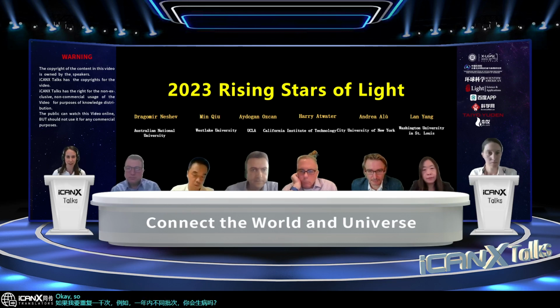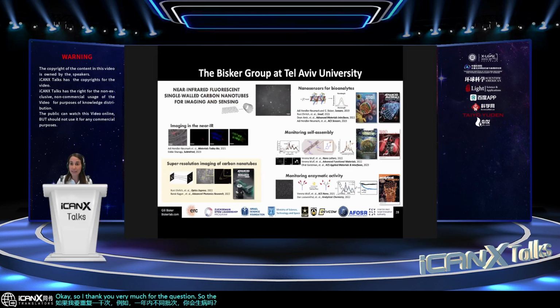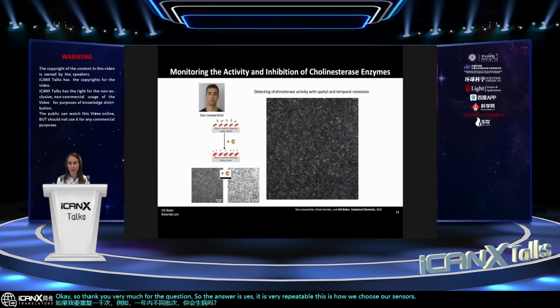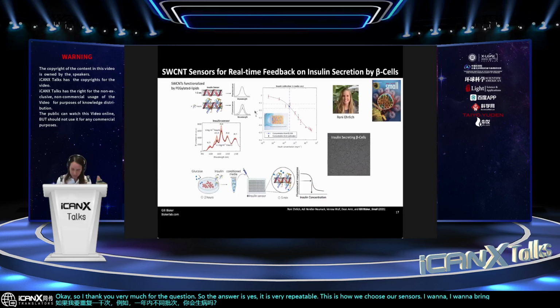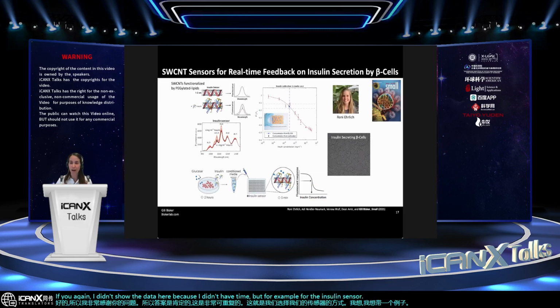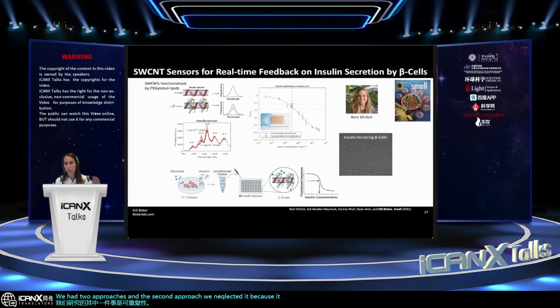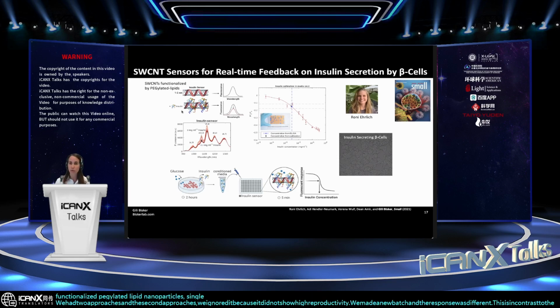Okay, thank you very much for the question. The answer is yes, it is very repeatable. This is how we choose our sensors. I want to bring one example. I didn't show the data here because I didn't have time, but for the insulin sensor, we tried different approaches to find the best one, and one of the things we looked at is reproducibility. We had two approaches, and the second we neglected because it did not show high reproducibility. We made a new batch and the response was different. This is in contrast to the functionalized pegylated lipid nanoparticles, single-wall carbon nanotubes, that showed high reproducibility, and every batch that we made showed the same response. So this is definitely something that we take into account.